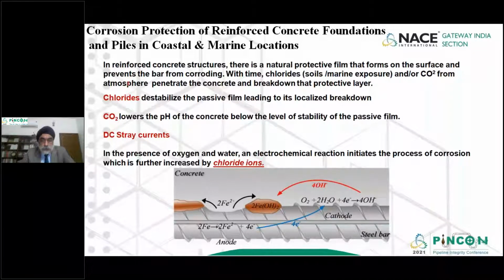Normally, as I said, steel in concrete does not corrode because the cement provides a natural protective film which prevents the steel rebar from corroding. The elements which cause corrosion on the rebars are primarily three. Chlorides: chlorides destabilize the passive film, leading to a localized breakdown and causing rapid corrosion on the rebar.